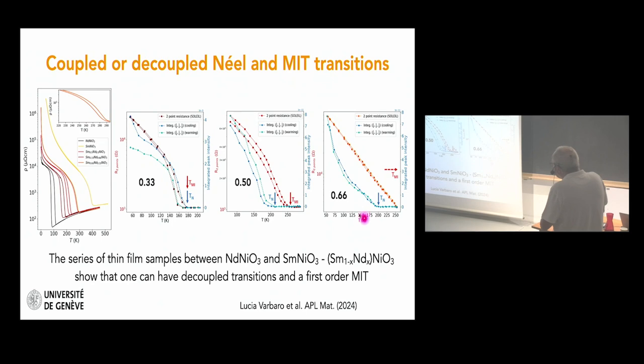So these are the 3 different compositions of these solid solutions. The resistance versus temperature and the integrated peak intensity. So for this sample, the 2 transitions are coupled. But what we find is that these 2 samples have decoupled Néel and MI transitions, also still showing hysteresis. So the conclusion of this recent study is that the order of the transition is not linked to the fact that these transitions are coupled or not.